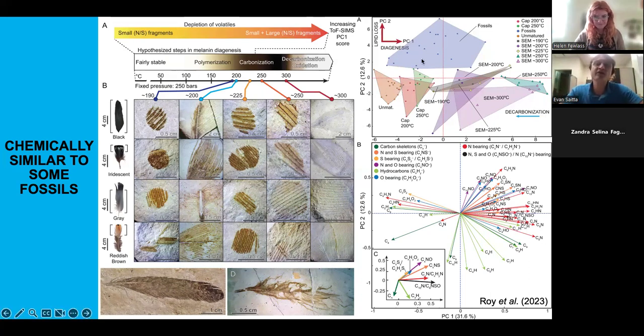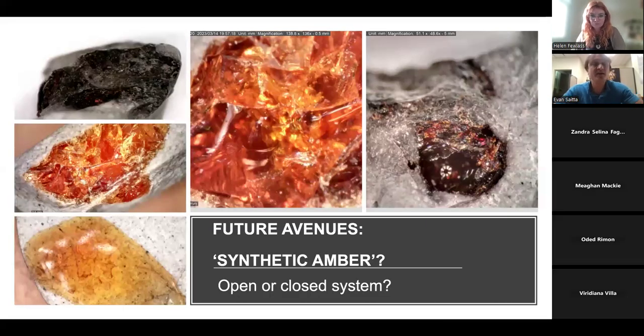And the only real difference between these experimental samples and the fossils, which are up above, is in their lipid content, which might be due to the fact that we did not expose these samples to decay or weathering. And so the lipid loss we see in fossils might be due to some of these other processes that we could in the future experimentally simulate, but we did not there.